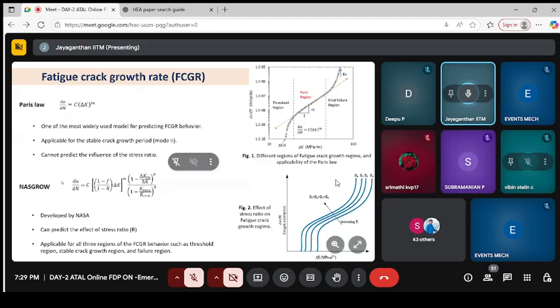That's why we use Paris law. The da/dN, where a represents crack length, shows how the crack size is growing as a function of number of cycles. That is being captured through Paris law. You can look at the extreme right side picture. We want to quantify the crack growth rate as a function of, you can see, delta K.